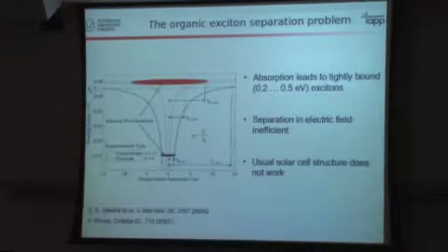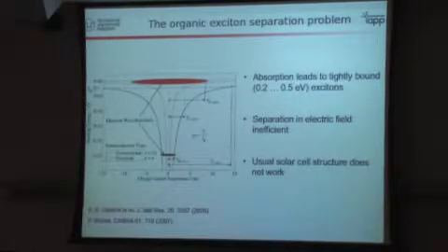The other issue is the fact that the exciton is very tightly bound. This is a nice diagram from Moritz Riede, which shows an organic exciton, which is basically a nanometer or so large. It's on one molecule, and its binding energy is something like 10 times kT, compared to an exciton in silicon or gallium arsenide, which is 20 nanometers or so large, and is much less than kT. You have a problem here. You cannot really separate the charges.